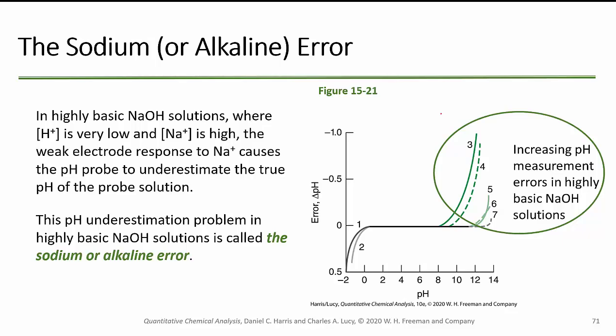So here's an example of some of these errors in highly basic sodium hydroxide solutions where H plus is low and sodium is very high. The weaker electrode response to sodium causes a pH probe to underestimate the true pH of the solution. So it's artificially low. And here are some different probes from different manufacturers showing what this error in pH is as a function of pH. So if you go up to a pH of 12 on electrode number 5, right, you're thinking it's going to be 12 and it's only going to measure 11.5. Right? Number 3 over here is going to be even worse. It's only going to measure 11.